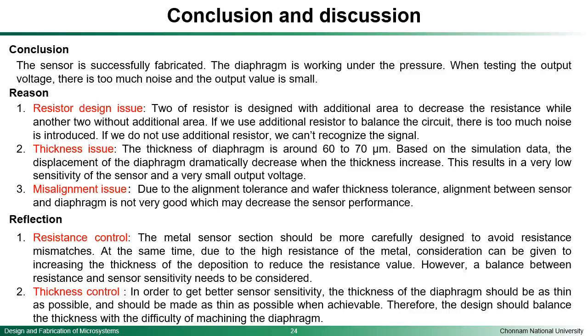Based on the possible reasons, we did some reflection. The resistance control is a very important parameter in our sample. The metal sensor section should be carefully designed to avoid any mismatch of the resistance. At the same time, due to the high resistance of the metals, consideration can be given to increasing the thickness of the deposition, so we can increase the metal thickness to decrease the resistance value.